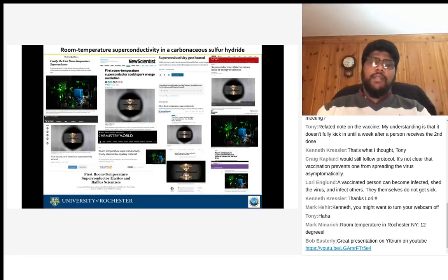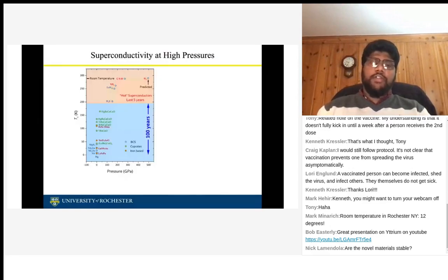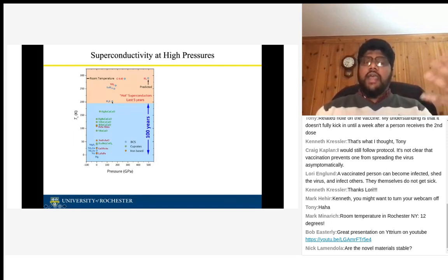If you look at this graph right here, this is the pressure versus the transition temperature. For more than 100 years, from 1911 to 2015, we were in the really low temperature region. 150, 160 was the maximum transition temperature ever found. But in 2015, the discovery of hydrogen sulfide becoming a superconductor at 200 Kelvin changed the whole game. People started to really think about hydrogen as a promising material to achieve a room temperature superconductor, because it's predicted to be a room temperature superconductor right here.